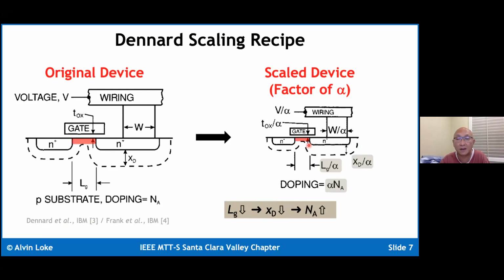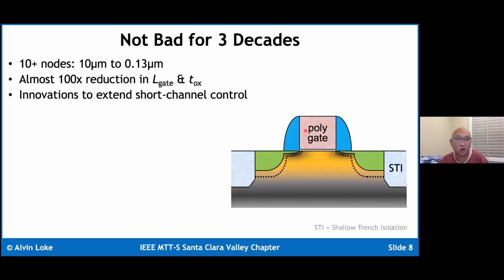Okay, and when the doping concentration goes up, that will invariably cause the threshold voltage to drop, or sorry, to increase. Which necessitates that the oxide thickness gets less and less to recover more gate control of the channel charge, and therefore bring your VT down from being unacceptably high. And when you've got thinner gate oxides, naturally electric fields go up, which requires you to reduce the voltage in order to prevent device breakdown. So this recipe has worked very well for about 3 decades. And the net result was about 2 orders of magnitude reduction in the gate length and the oxide thickness. But it hasn't been completely quite so linear.